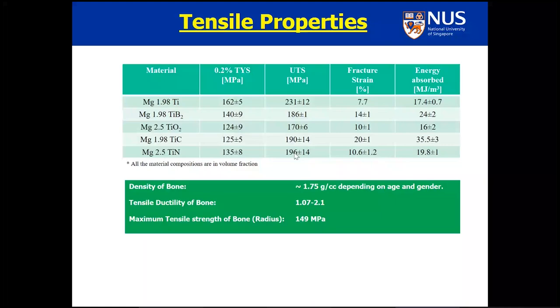So we tested a number of nanocomposites with biocompatible elements that we are putting in the body. And the first thing we did was to see whether the properties of this composite system are better than the mechanical properties of the bone, which is at 149 megapascal tensile strength. And all the properties that we got were higher than that. The ductility of the bone is between 1 to 2, and all the ductilities we got were higher. Similarly, the compressive properties were superior.